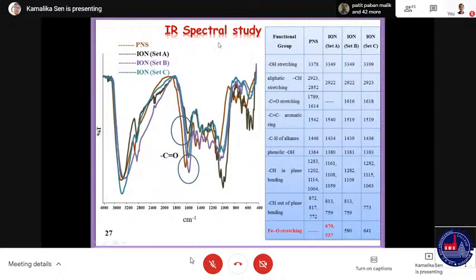This is the FTIR spectral data. This is the PNS, peanut skin extract. You can see a lot of carbonyl group stretching vibration in PNS only. However, in set A, which is prepared in absence of gamma irradiation, the carbonyl group is less. That means without irradiation, the involvement of carbonyl group is less.